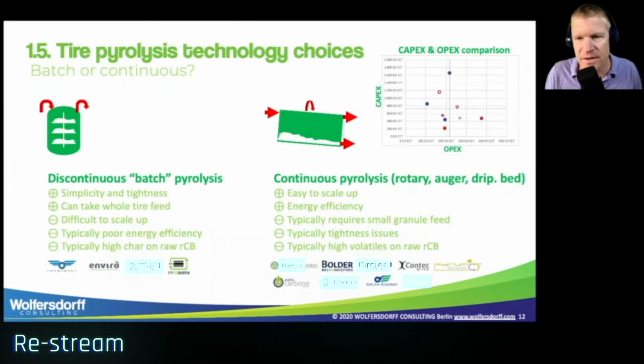Very often there's multiple auger steps in the reactor. It could be a dripping bed reactor. There's one company, Pyrum, that has a dripping bed reactor with no moving parts. So there we can have a continuous system which is really airtight, which is a good advantage. Continuous pyrolysis kilns are easy to scale up. They have a good energy efficiency. However, as I said, typically they require a very small granulate feed. And typically there's tightness issues.